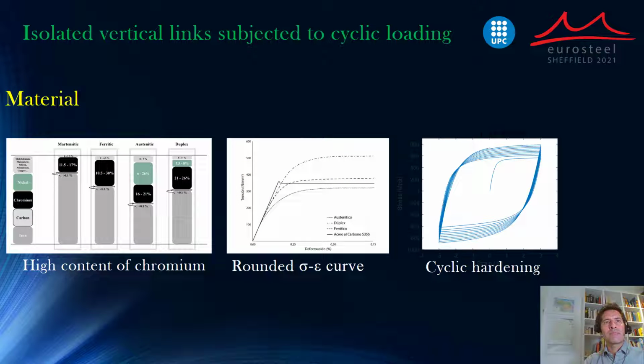So the material, as we mentioned, is stainless steel. It's an alloy which contains a high content of chromium. An important characteristic for this study is the rounded sigma-epsilon curve. Also, one of the characteristics that is relevant here is the cyclic hardening. Stainless steel hardens when it's subjected to cyclic loading up to certain points, and it needs to be properly addressed when modeling.